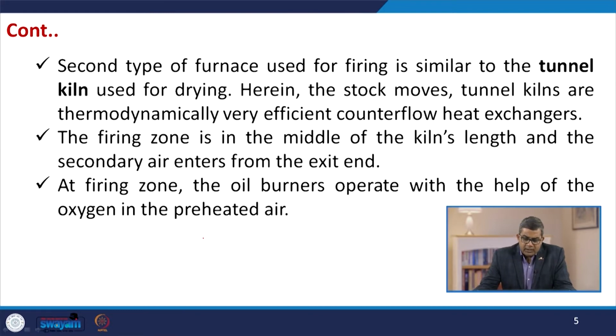Now, the second type of furnace used for firing is similar to the tunnel kiln, which we discussed in the previous lecture, and that is used for the drying. In this, the stock moves, and tunnel kilns are thermodynamically very efficient counterflow heat exchangers. The firing zone is in the middle of the kiln's length, and the secondary air enters from the exit end. At the firing zone, the oil burners usually operate with the help of oxygen in the preheated air. From the firing zone, the combustion products carry heat and pass through the preheating zone.